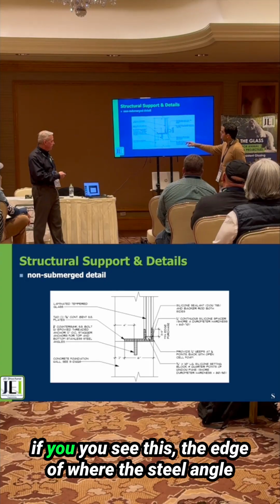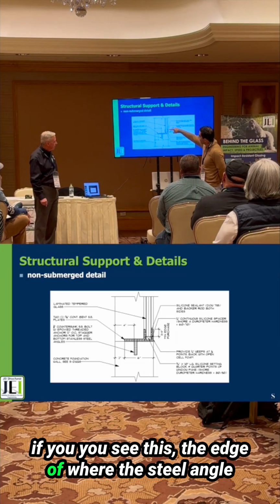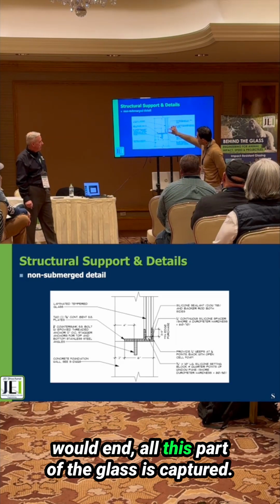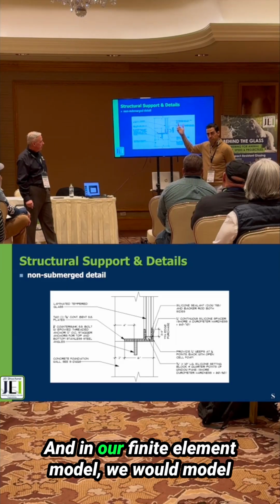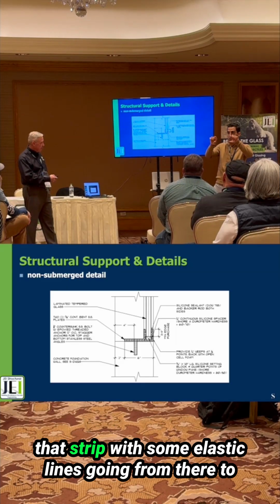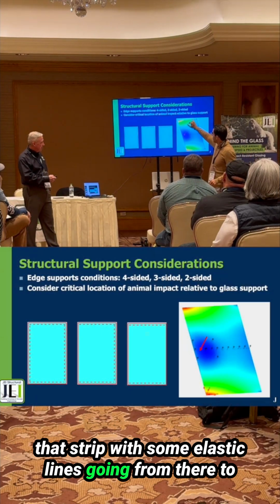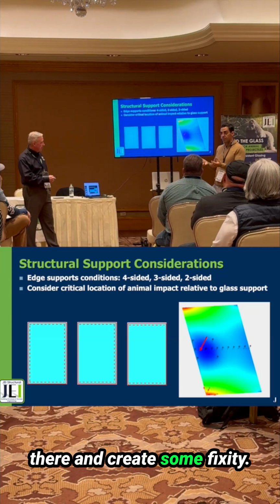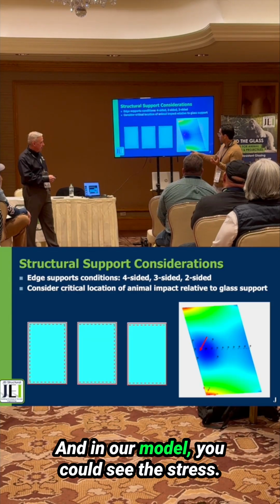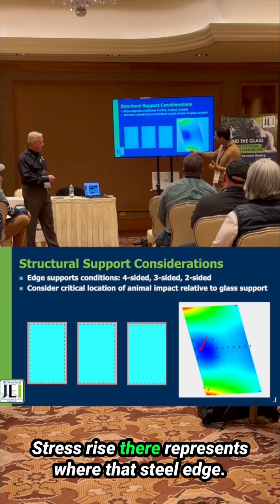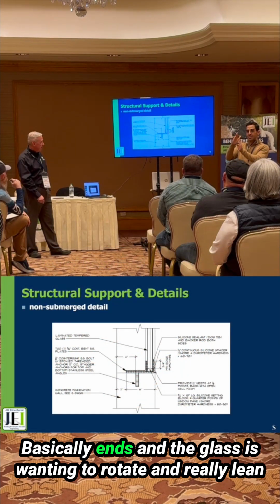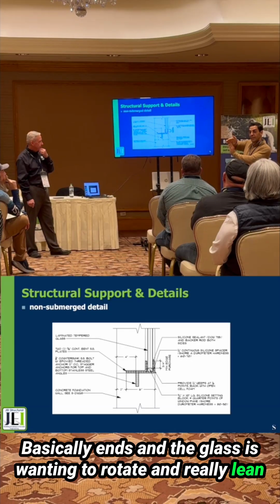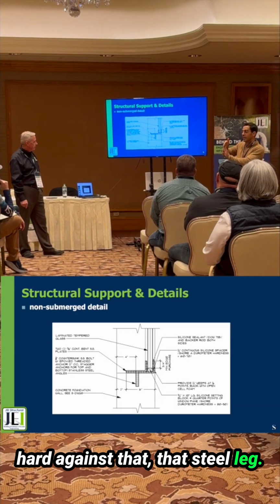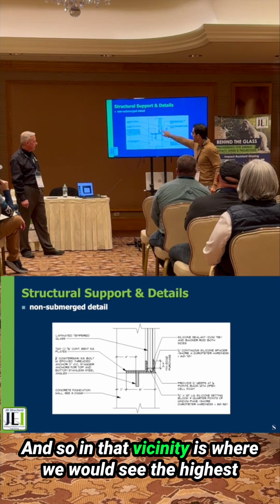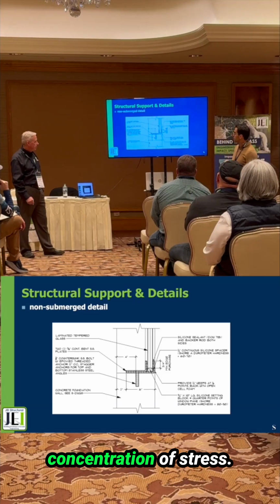Oh, and real quick, if you see this, the edge of where the steel angle would end, all this part of the glass is captured, and in our finite element model, we would model that strip with some elastic lines going from there to there, creating some fixity in our model. You can see the stress riser there represents where that steel edge basically ends, and the glass is wanting to rotate and really lean hard against that steel leg. And so in that vicinity is where we would see the highest concentration of stress.